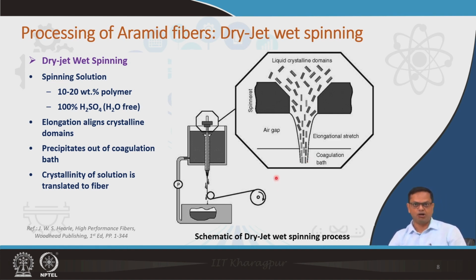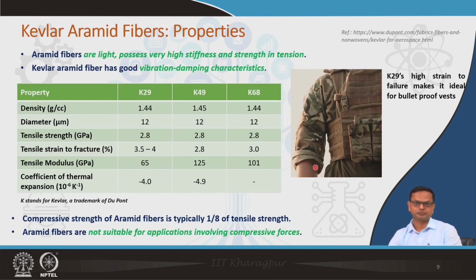Coagulation bath is nothing but basically low temperature water. That basically washes off the extra H2SO4 which was used earlier to go through these particular steps from random coils to ultimately get this liquid crystalline state. So, to wash off that extra H2SO4, this coagulation bath is required, and that is the part of the wet spinning. So, you have dry spinning and wet spinning, and that ultimately leads to the formation of the aramide fiber, from aramide material to aramide fiber. I hope the process is clear to all of you.